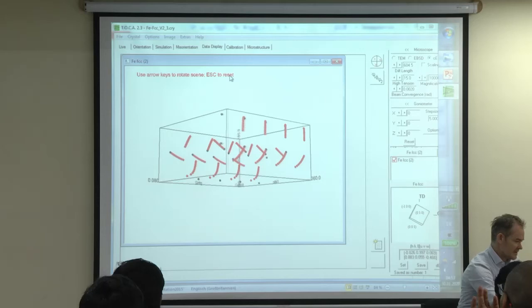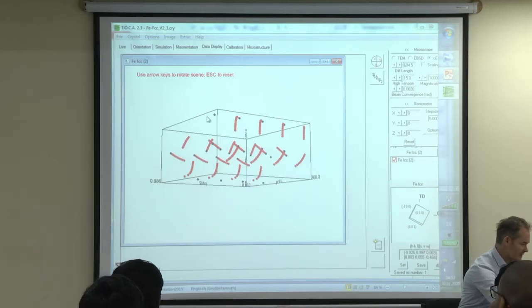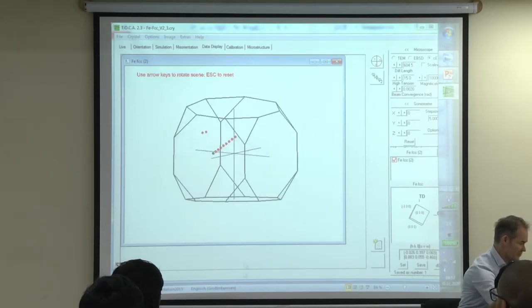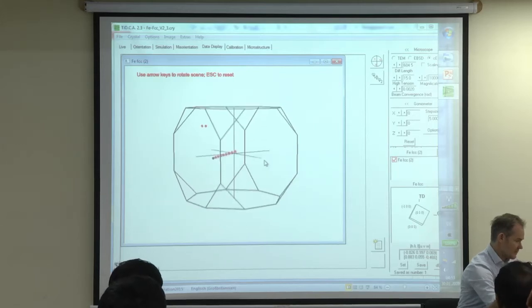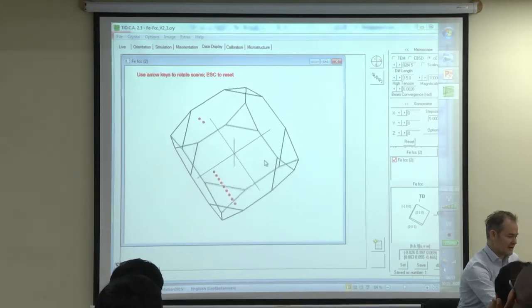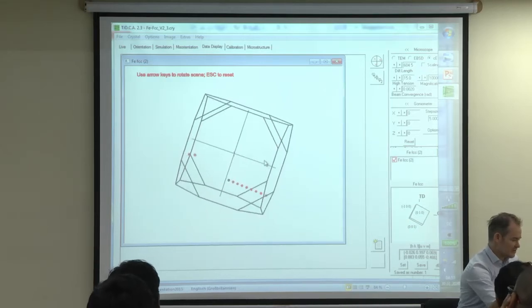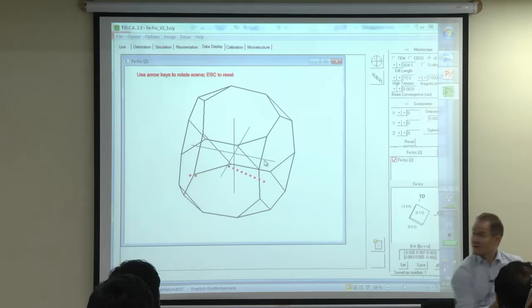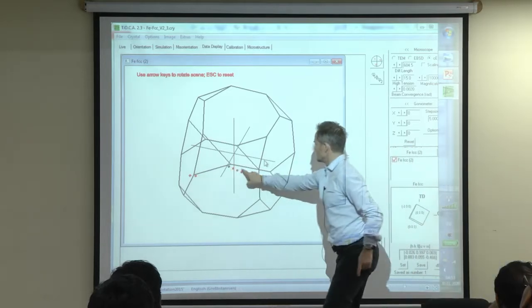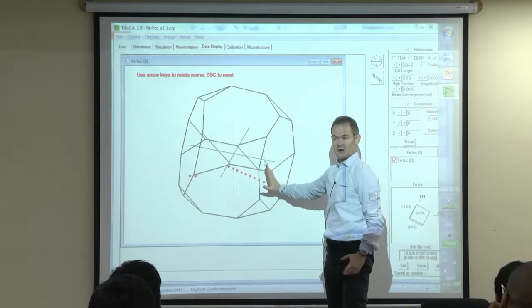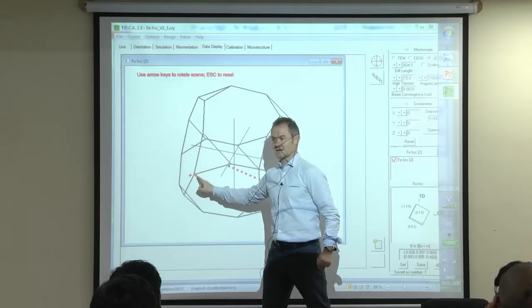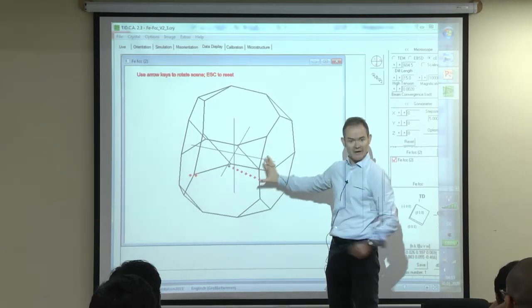Okay, good. And now let's look at the same thing in Rodrigues space. Okay, so that's the Rodrigues space. And you see it's just a straight line. The straight line starts coming out. It started here, and then it jumps when it touches the surface. It jumps in from the other side again. And it's just a straight line, very nice to see.